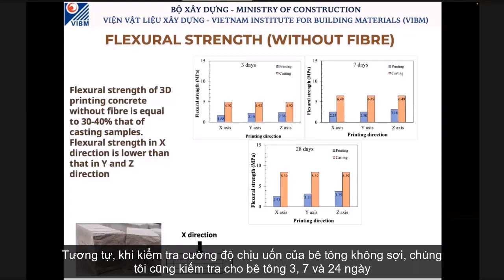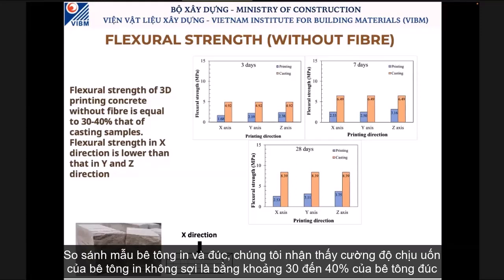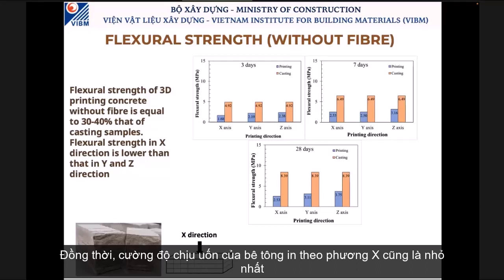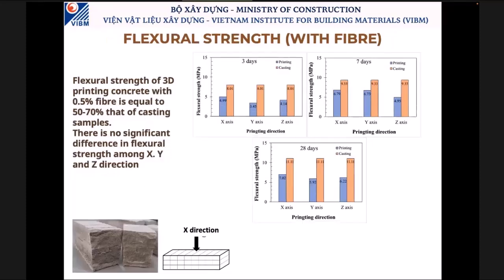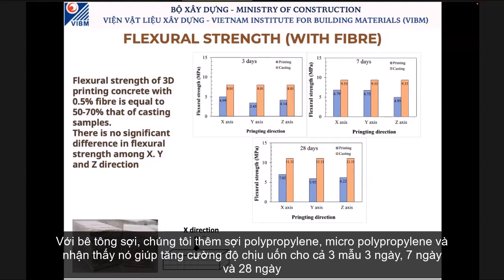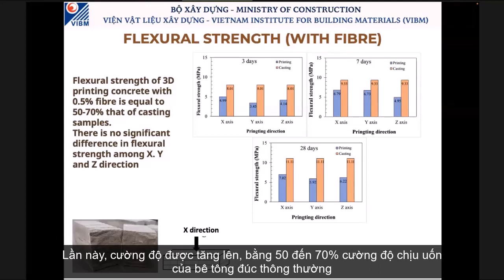This is without fiber, and we also measure the flexural strength at 3 days, 7 days, 28 days, and we compare the printed specimen and the cast specimen, and we found that the flexural strength of 3D printed concrete without fiber is equal to 30 to 40% that of cast specimens, and also the flexural strength in the X direction is the lowest result. With the fiber, we add micro polypropylene fiber, and we found that it improved the flexural strength at 3 days, 7 days, and also 28 days. And the flexural strength of the fiber printed specimen improved to about 50 to 70% that of cast specimens.